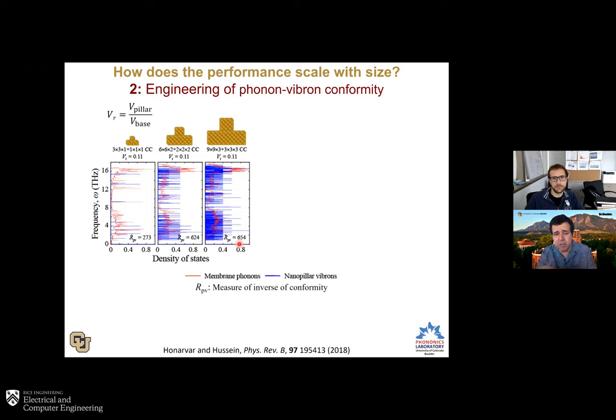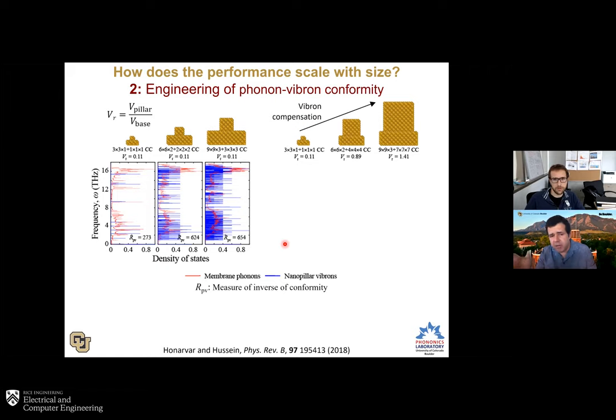So in fact, that was quite a setback, because you see, as we increase the unit cell size proportionally, we lose that conformity. So we've worked on it quite a bit, because it was not a very encouraging piece of news, at least temporarily, because it would suggest that we can't scale this concept up. However, I should say, happily, we were able to find that rather than grow the size of the unit cell proportionally, and when I say grow, I mean in our mind, conceptually, in our models, if we were to grow the pillar part at a higher rate than the base membrane part, so the VR, the volume fraction, gets larger, what we call vibron compensation. So we're compensating with more and more vibrons as we scale up.